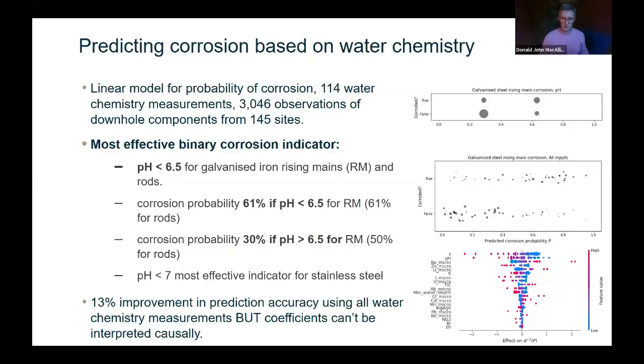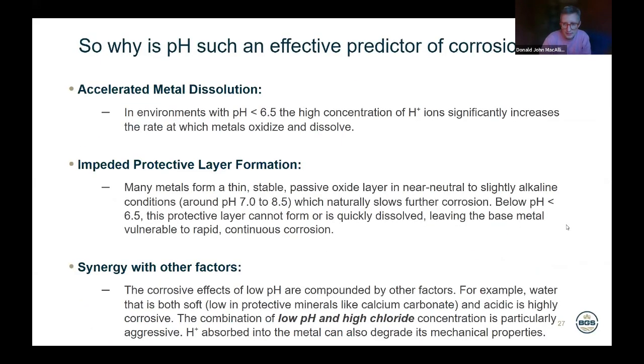We also looked at the full model where we put all of our water chemistry results in, and we did see an improvement in our prediction of corrosion, but it was quite a small improvement overall, only 13%. And actually, one of the main factors out of all of those salinity and water chemistry indicators was still pH in the models where we had everything in. So this is really good statistical evidence for the effectiveness of pH 6.5 as a predictor of corrosion in rural water supplies. Maybe we could move on to the next slide.